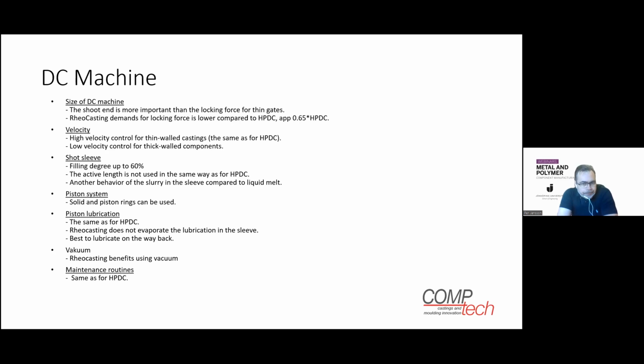Then we have the velocity, the velocity of the metal or the piston, so to say. If we talk about thin wall castings, we use a higher velocity, similar to the type of shots you find in a conventional high pressure die casting shot. But in thick wall components, it's very important that the machine can handle very low velocities, which is not common to use in conventional high pressure die casting. And as I said, the shot sleeve, the material does not behave in the same way as when you pour in a liquid metal, where the metal runs all the way up to the parting line of the die.